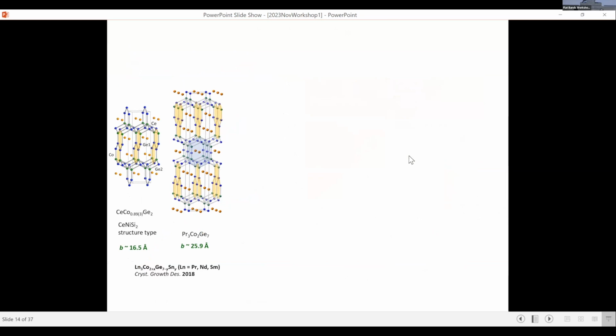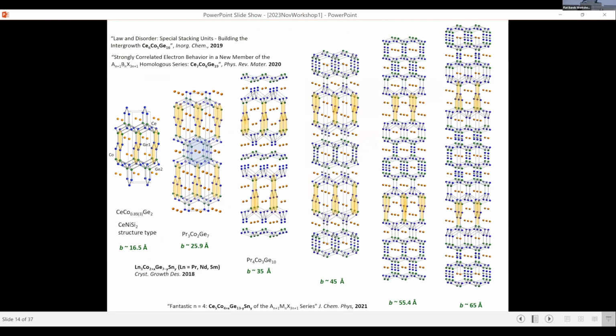Okay, it's been reported, lots of compounds, and we also make the praseodymium cobalt germanides. And basically, we could grow single crystals, and it turns out that this is a new homologous series. Now this new homologous series is exciting because some of the structural subunits are actually quite evident in known materials. The yellow highlighted is the AlB2 type. If you tilt your head, you can actually see it. And another feature is that you have the BaAl4 type, but now with the non-centrosymmetric subunits.